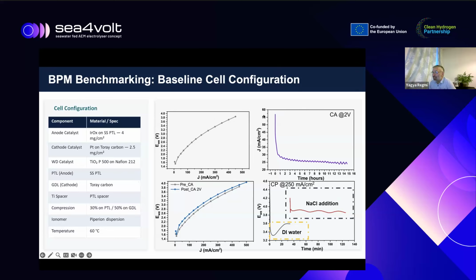As you can see from here, when we started really early on, the DI water dissociation, the bottom right graph on your screen, when you feed just DI water, the cell potential is slightly above 3 volt. But as soon as you start, this is simulated seawater now, we're calling 0.5 molar sodium chloride simulated seawater, the cell potential increases quite rapidly. Next slide, please.